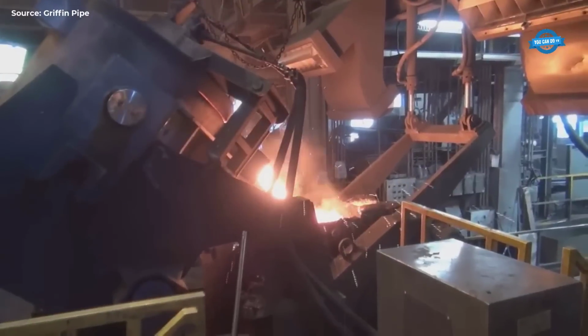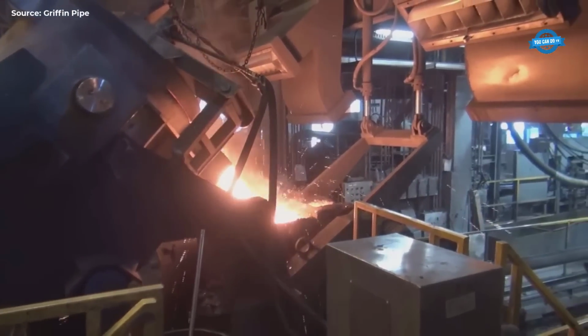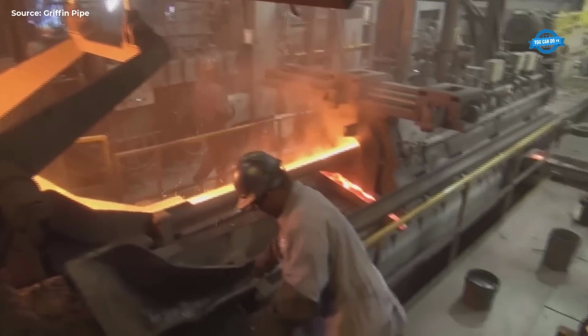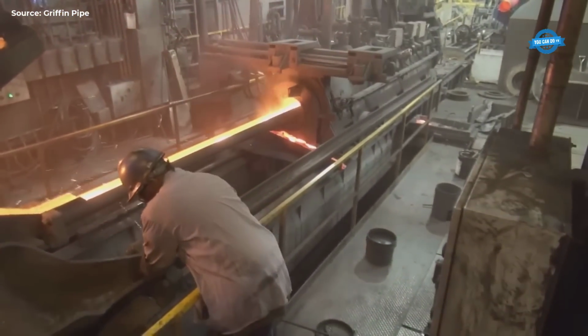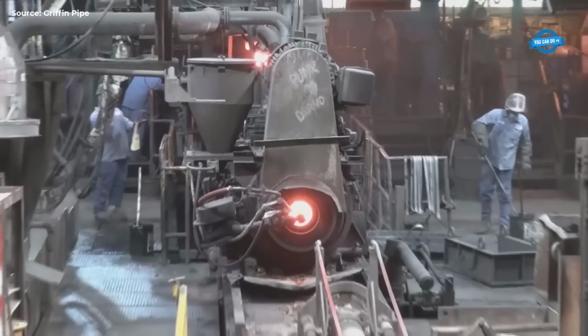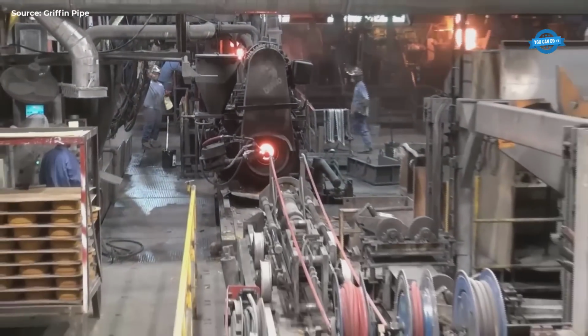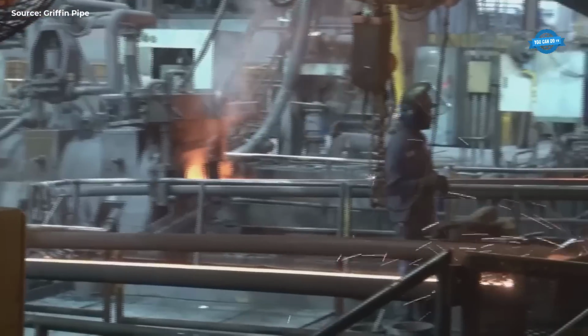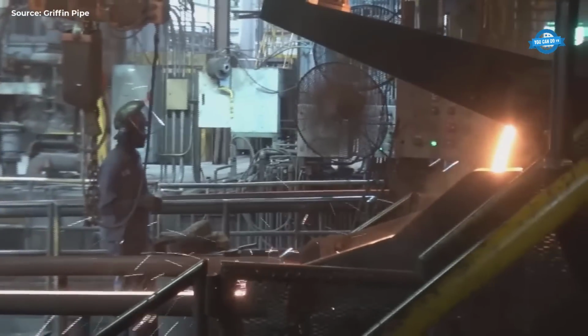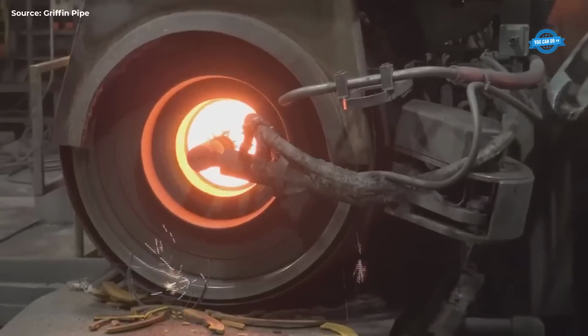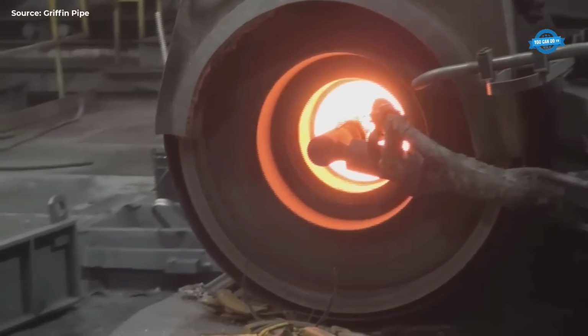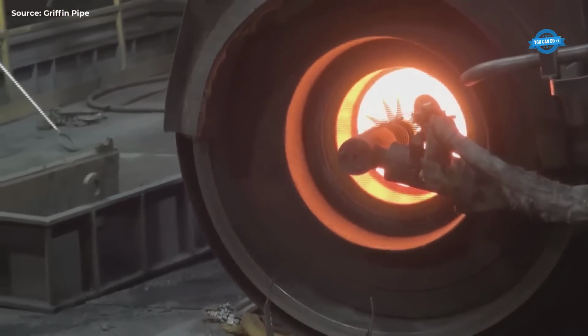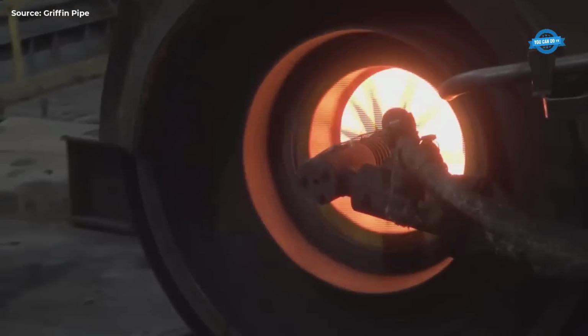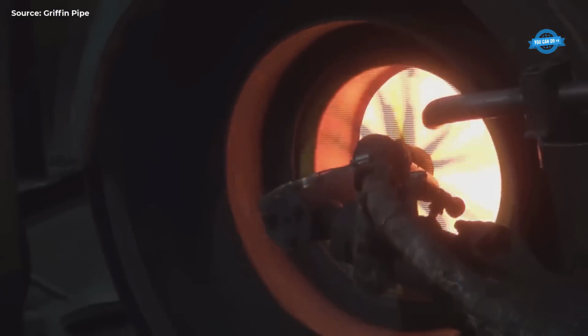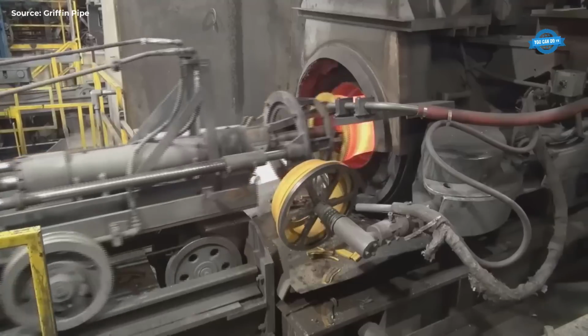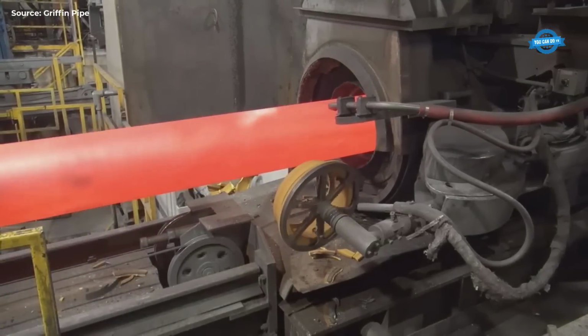Pouring and spinning. The actual casting starts when the operator tilts the pouring ladle, allowing molten iron to flow down a chute into the mold. As the iron fills the mold, the operator moves the mold assembly along the machine bed on rails. The mold rotates horizontally at high speeds, creating centrifugal force that pushes the molten iron against the mold walls, ensuring uniform thickness and forming the pipe barrel. This process typically takes 30 to 90 seconds, depending on the pipe size and class.